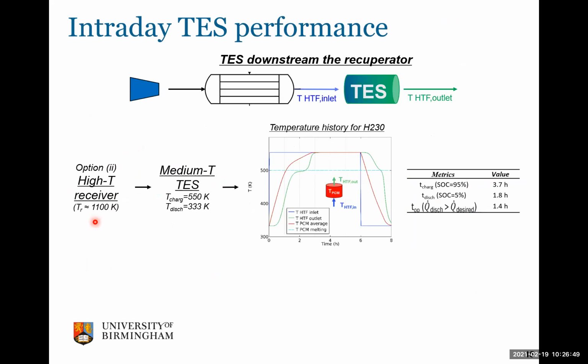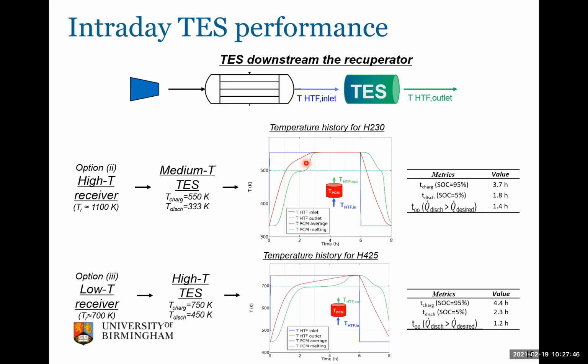So obviously we carried out a more numerical analysis of the actual performance of this component with a couple of material options. Here we look at pure metals as well as conventional molten salts, or actually mixtures of molten salts. And we have looked at the dynamics of the charge and discharge of this thermal storage system. When the storage was placed at the tail of the process, we had the opportunity to work with a storage duration of 4 to 6 hours during charge, and about 2-3 hours during discharge. Here, the blue line represents a synthetic inlet temperature to the thermal storage, which was used in the modeling work to predict the charging and discharging dynamics of the thermal storage for both of the materials selected.